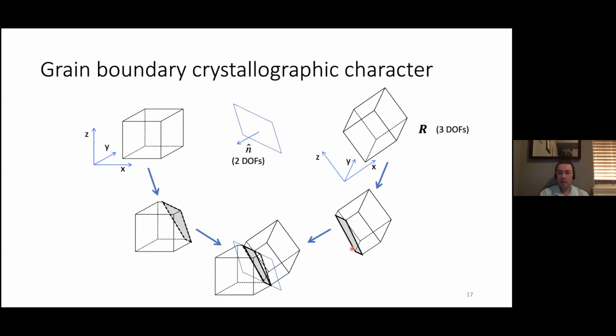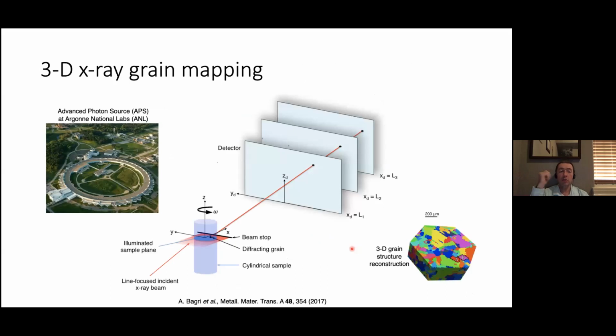Okay, in theory that's nice. How do we actually investigate that experimentally? Well, one way that you can do it is you can do 3D X-ray grain mapping. So the capability to do something like this is available, for instance, at the Advanced Photon Source at APS. This approach basically uses diffraction. It illuminates a sample of about millimeter scale dimensions. It then measures all the Bragg reflections from the different grains at different distances from the sample.